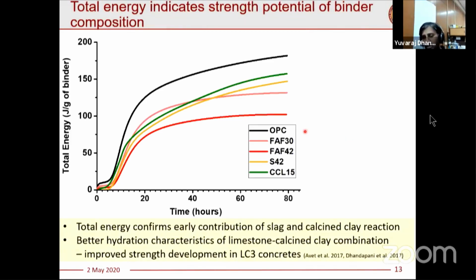So what it has to do with different binders. So here are some energy curves. What you see is the energy curves of all blended cements are much lower at the early ages. And you can see the slag and calcined clay binders start picking up by nearly 2 days and reach a much higher energy than your fly ash systems, which means there is an increased amount of reaction happening.